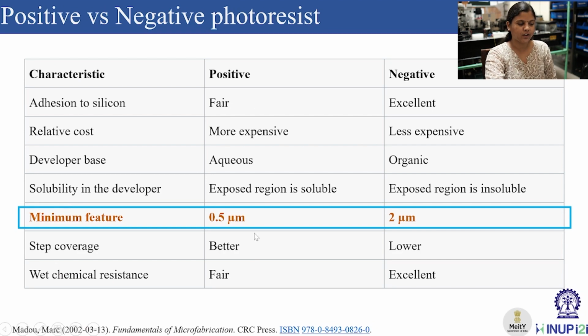If we see from here, for all the other optical parameters or photolithography process parameters kept same, we see that the resolution which could be achieved for the negative photoresist is less as compared to the positive. This happens because the cross-linked polymer in case of the negative photoresist can actually absorb solvent from the developer and it can actually swell. And due to this swelling process, the resolution which could be attained is actually limited.